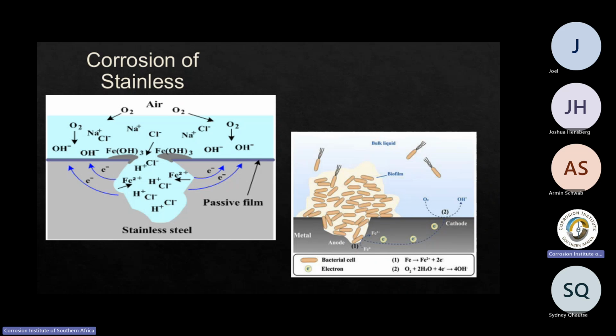But stainless steel is only as resistant as the passive layer remains on top of the surface. That chromium oxide layer that's on top of the surface needs to remain there for the stainless steel to work. And as soon as you start stripping off that layer, it's now exposed to different elements. Chlorides is one of the big things that start attacking the metals.